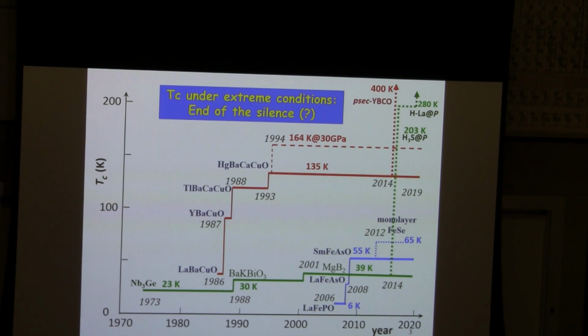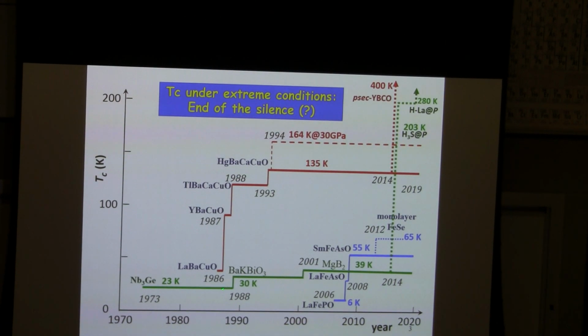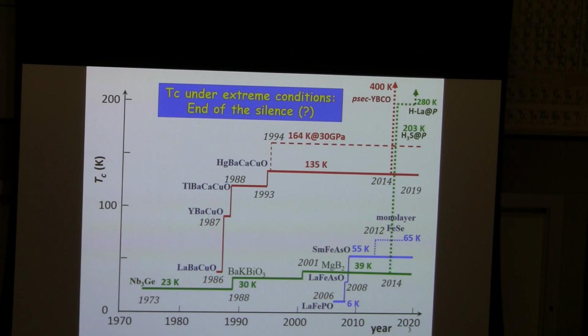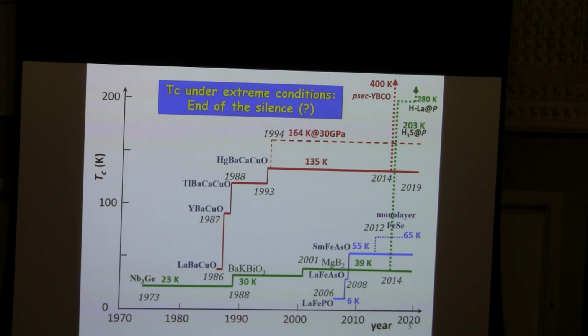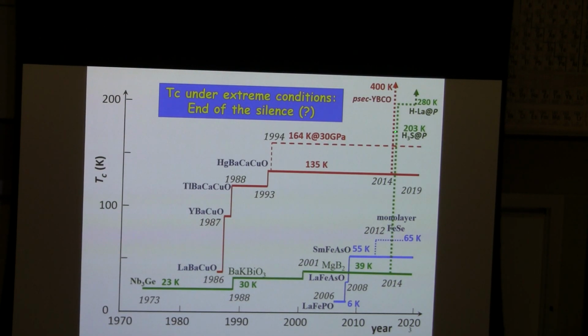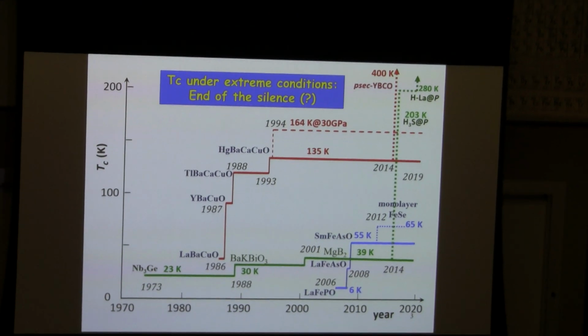You can see that cuprate in 2014 jumped up to 400 K. But the lifetime of the superconductivity is only on the picosecond scale. And another one that may be famous to you showed up from the conventional electron-phonon superconductor, incidentally in the same year, but the material was under very high pressure, and TC went up to almost near 300. I can show you some examples.